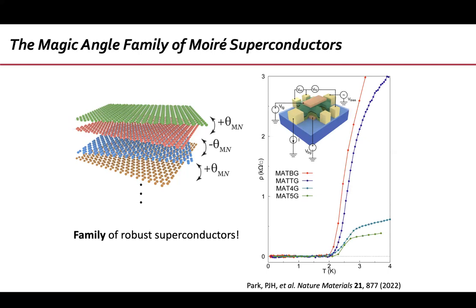You may think that you have more probability of errors, et cetera, but it turns out the phase space, the parameter space in density and displacement field over which superconductivity exists grows with the number of layers, for reasons which are not entirely understood. Maybe some of these extra bands help enlarge the parameter space where superconductivity occurs. This has been observed by several groups, including ourselves. We do not know exactly why.